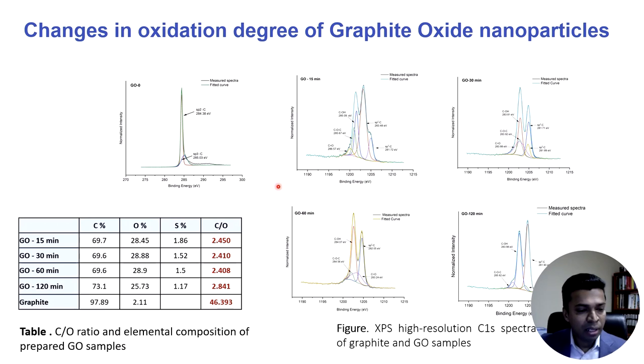So as you can see here, when we change the modification of the graphite oxide, we decrease the carbon to oxygen ratio, which means we introduce more oxygen functional groups compared to the graphite. And we confirm these different oxygen functional groups with X-ray photoelectron spectroscopy. And we recognize there are more hydroxyl groups, carboxyl groups, and covalently bound carbon in the oxidized graphite oxide.